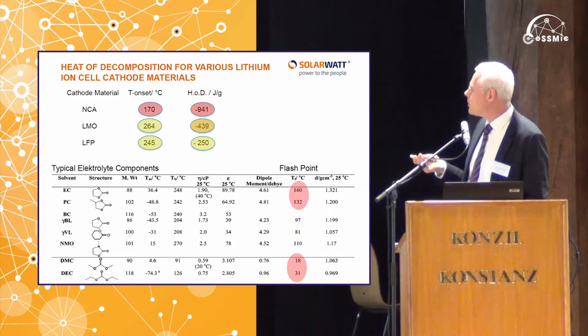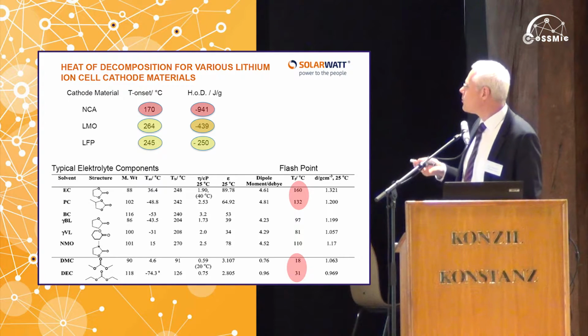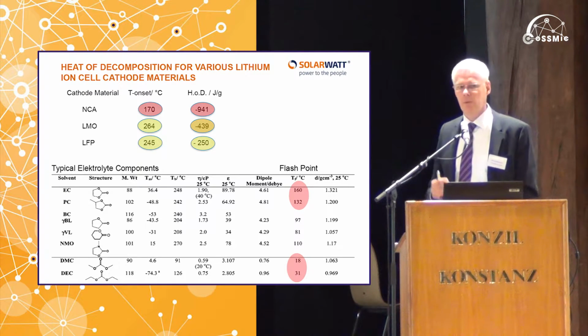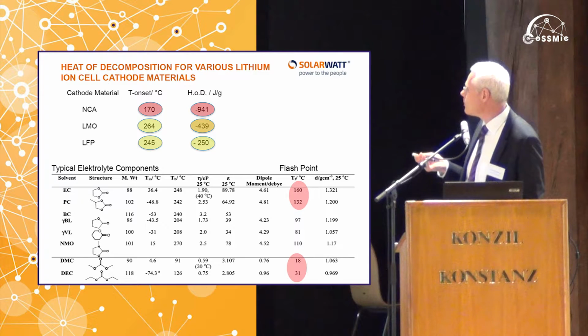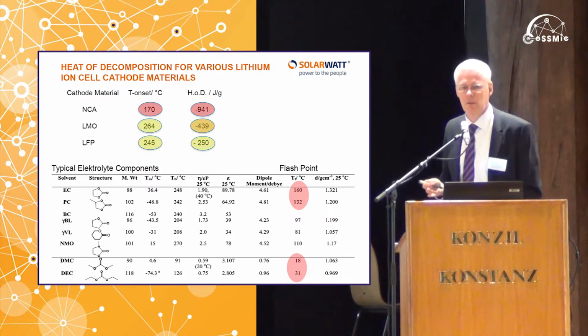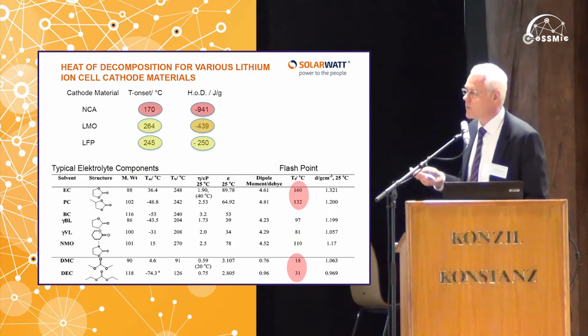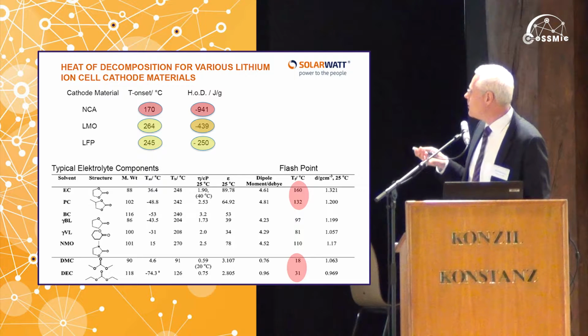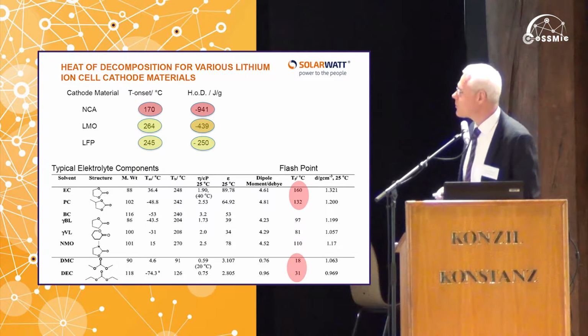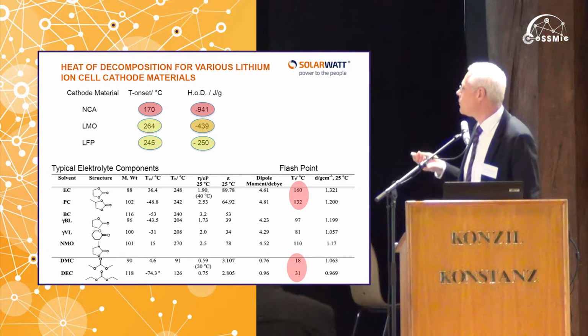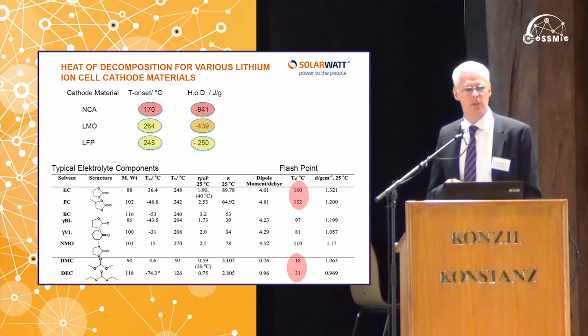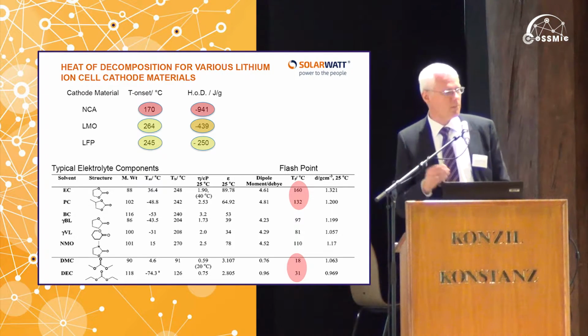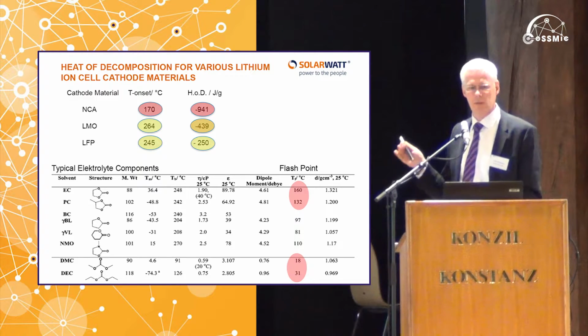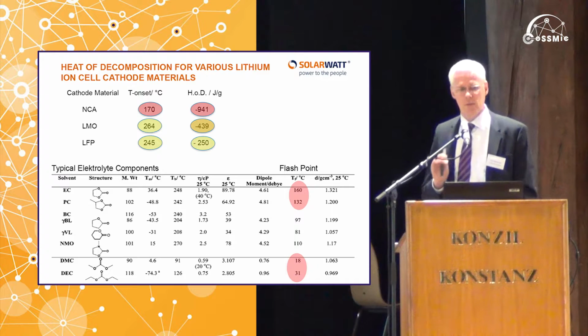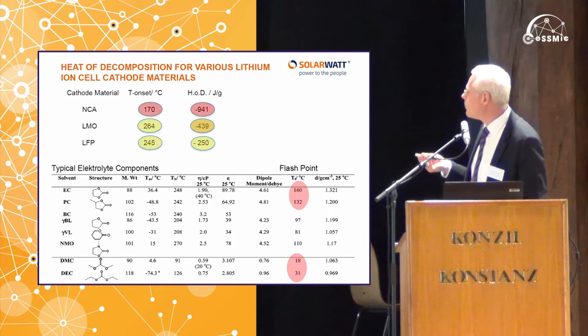And once this cathode material, NCA, which stands for nickel, cobalt, aluminium, reaches this temperature, you will observe a thermal runaway in the lithium-ion cell, and there is no way to stop this. And this is the heat of decomposition in joules per gram, which will be released then. And there is no way to stop the cell from emitting this heat. And here you can see that the numbers are different for different cell chemistries. And from a safety point of view, one would love to use the system with the lowest heat of decomposition, which is lithium iron phosphate. This is why sometimes home storage manufacturers using this tell their customers this is the safest technology that you can have, which is true if you look only at this number.